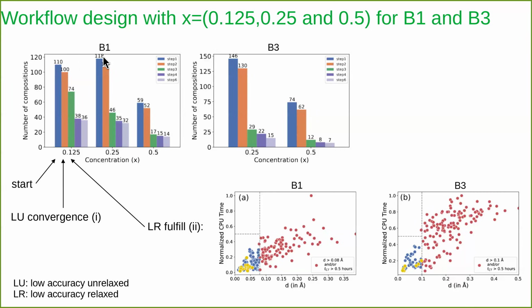So in summary, we started with 110 alloys for the B1 structure at this concentration, and then 146 in the B3 structure at this concentration, and then you will see the big difference in how many elastic constants we can actually store in our database. So it is really a huge, drastic thing. One needs to have a really clever workflow. That's what I want to emphasize here.